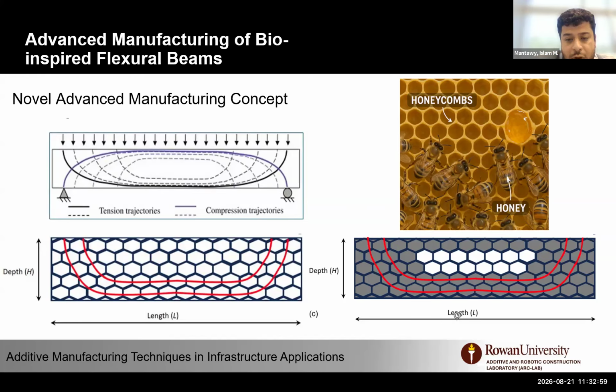And the idea here later on is that, using the stress trajectory, we can fill the cells selectively using a flowable material. But the difference between us and the rest is we actually immediately fill it with the same system, a 3D printing system, by changing the rheology of the material. So this is just a schematic here.